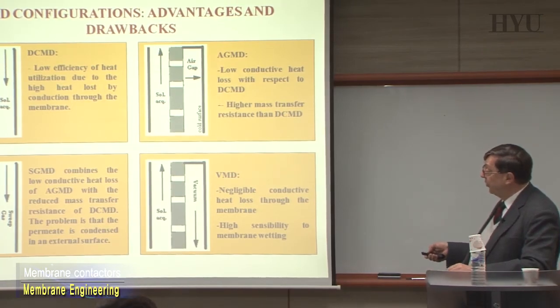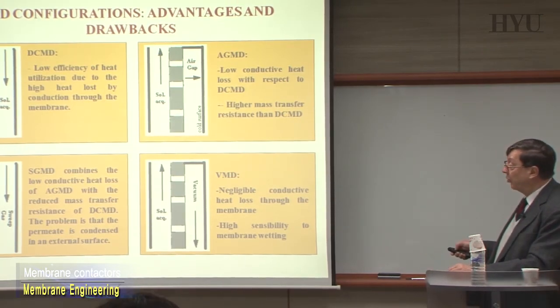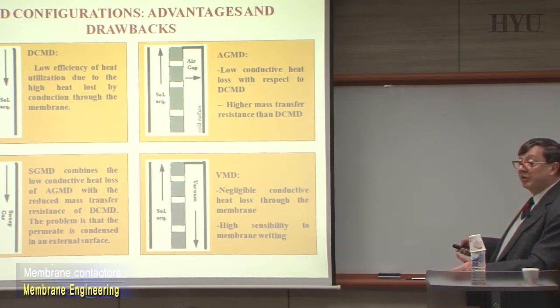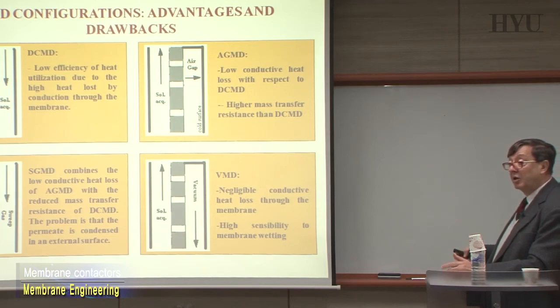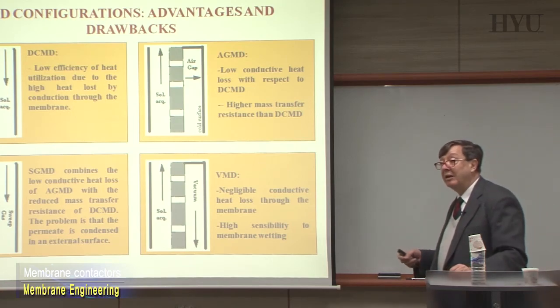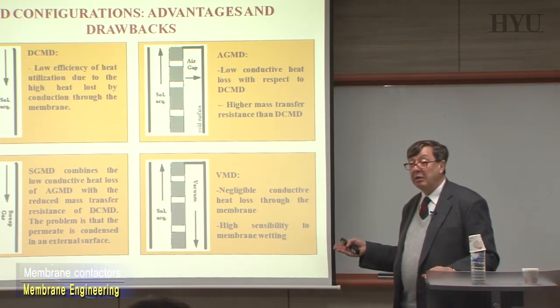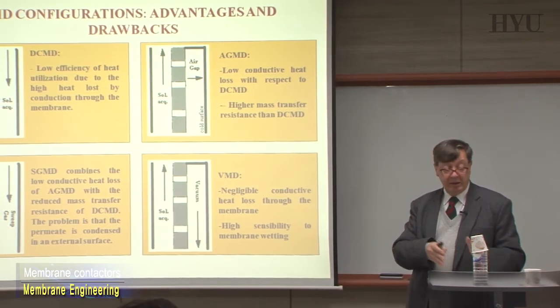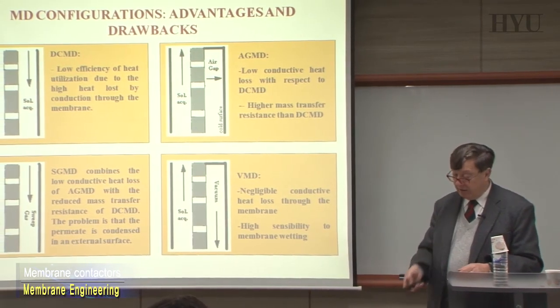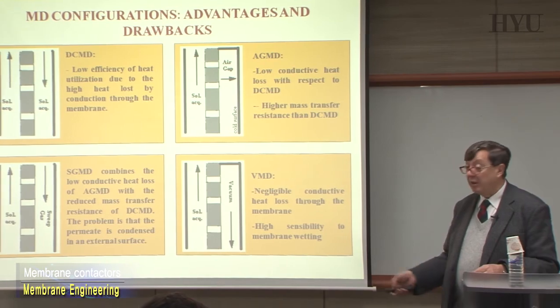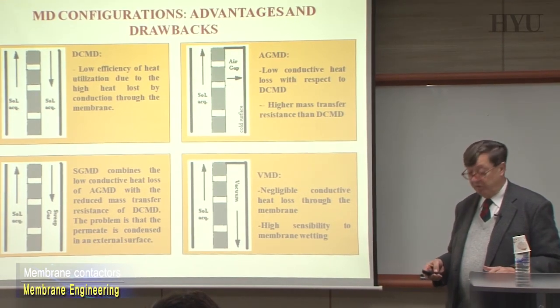In the vacuum, for example, as I was mentioning before, we have a negligible, very, very low conductive heat loss through the membrane. This is relatively not very important. However, in this case, the membranes are very sensitive to any problem of wetting. Wetting means that your hydrophobic character can slowly disappear and become hydrophilic. And that can be a problem that you have to solve.